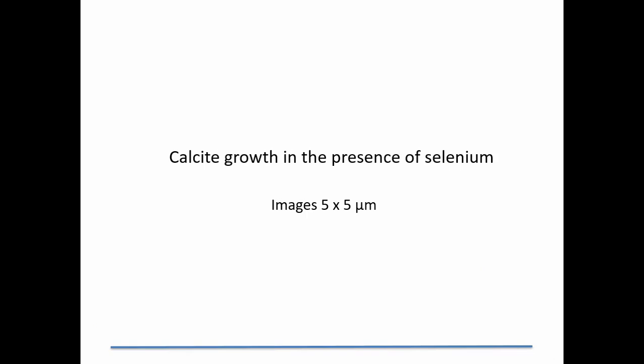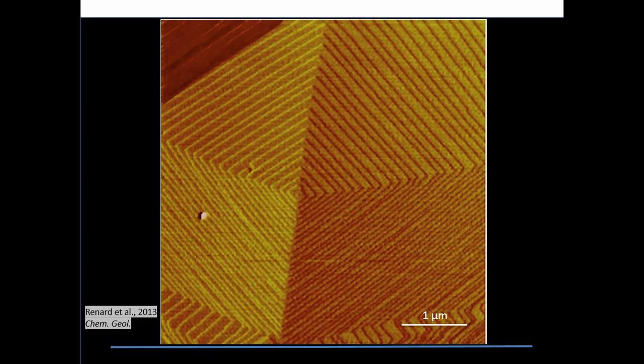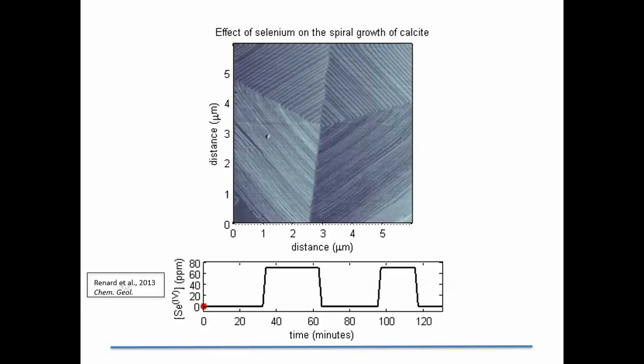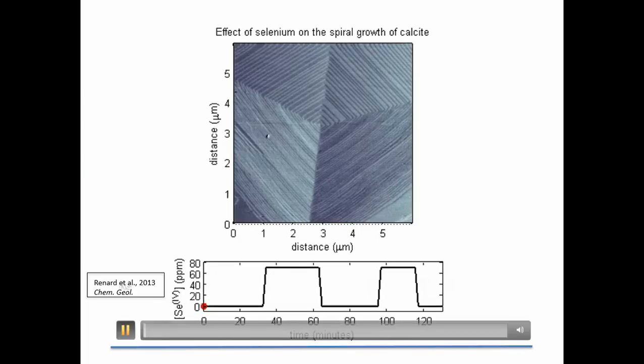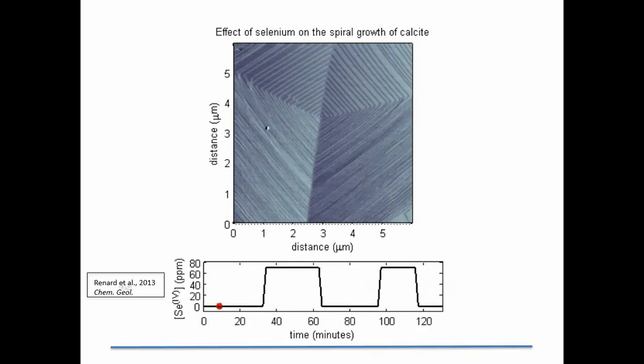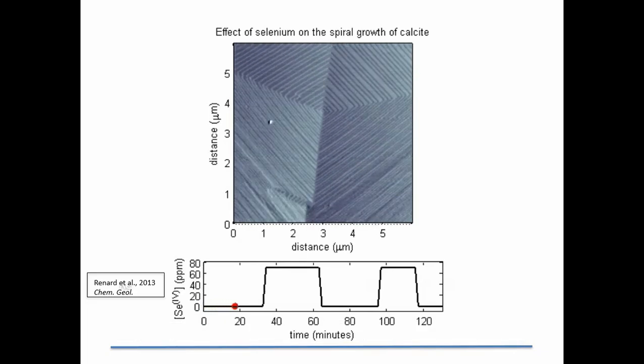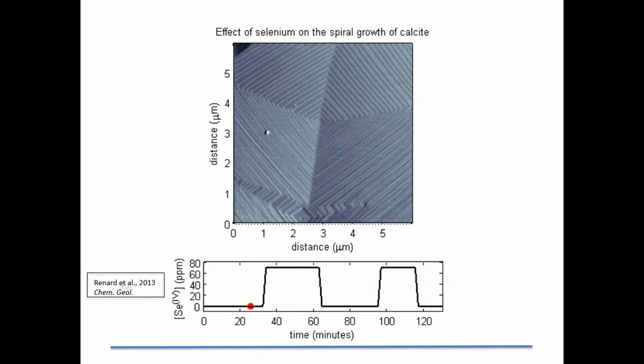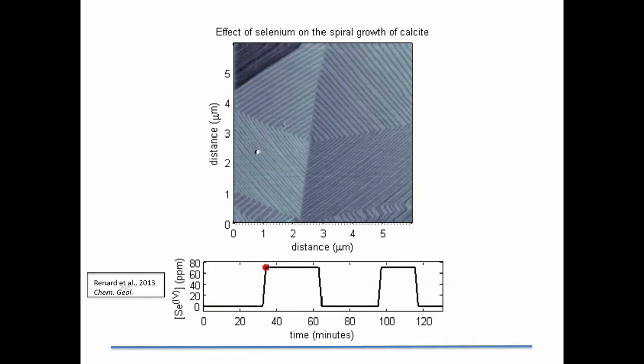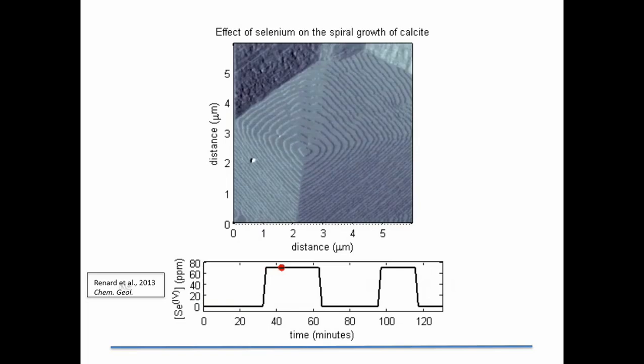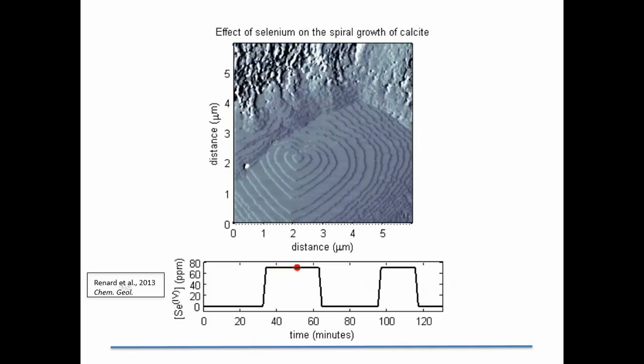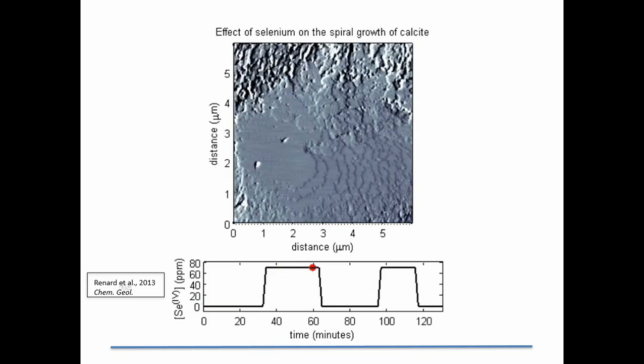Before I go on to that, I'm going to look at calcite growth in the presence of selenium, because that's related. Okay, there's another lovely spiral on calcite with a calcite growth solution. Let me see if I can get this to go. I'm going to add the growth solution plus the selenium in ppm amounts. I'll show you in the next slide. And we have a beautiful spiral whose shape changes, and we get the formation of a lovely heart. One side is being pinned.